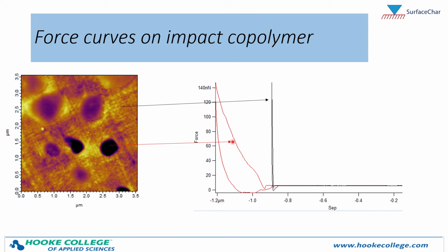And I can immediately see some significant differences between the force curve on the thermoplastic matrix and on the rubber. First, just to note what we're plotting here. So we're plotting force in units of nanonewtons versus the tip sample separation, which is in units of microns. What you actually collect is deflection in volts versus Z piezo motion, and you have to do some calibrations and conversions in order to get to a force versus separation plot, but this is ultimately the plot you want to